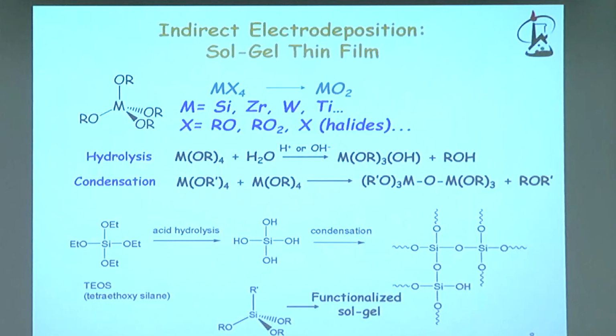The big advantage of sol-gel that I guess most of you are familiar with is that you don't have to start with materials that have 4 different ligands that will hydrolyze. You can replace one or more of them with other groups. For example, if you have a silicon-carbon bond, this will not hydrolyze. Because of that, your silica will always have, on one silicon atom, a group that will give different properties to the silica. You can make, for example, hydrophobic silica, you can make charged silica, and so on. That's a big advantage, besides the fact that you don't do that at high temperature.